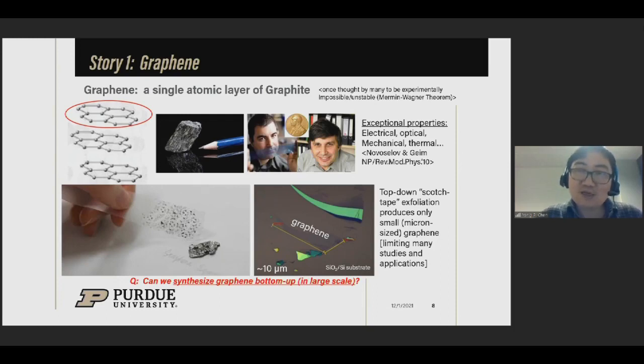Many actually thought experimentally it was impossible to create this isolated single-layer graphene, because a powerful theorem called the Mermin-Wagner theorem says that in 2 dimensions, long-range order such as crystalline order may be unstable. But nature often has a way to outsmart, to get around this kind of constraint. As we all know, about 17 years ago, Geim and Novoselov, the pioneers of graphene, used the so-called low-tech Scotch tape method to exfoliate monolayer graphene from graphite and revealed many interesting properties of these materials, which I won't go into.